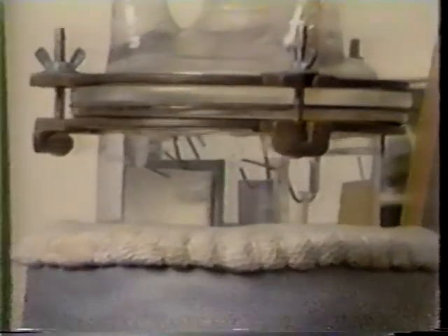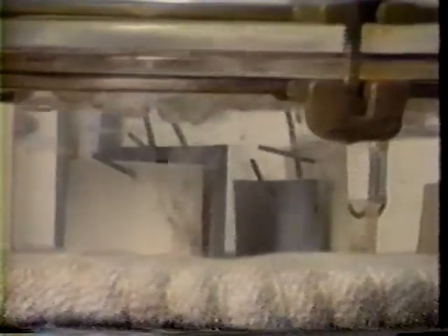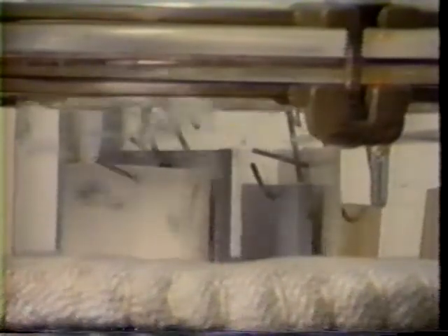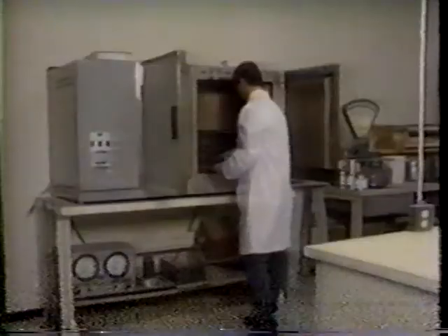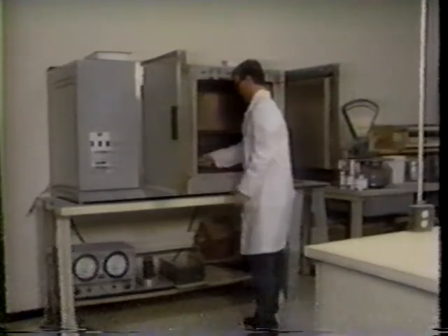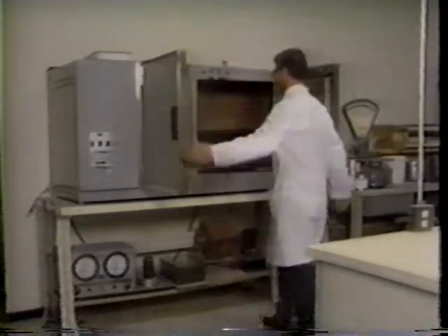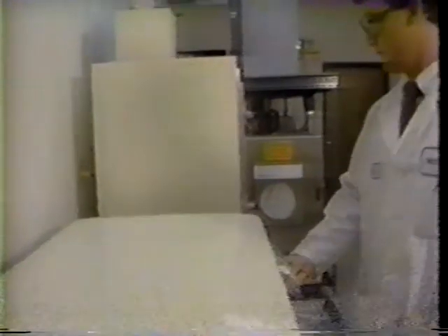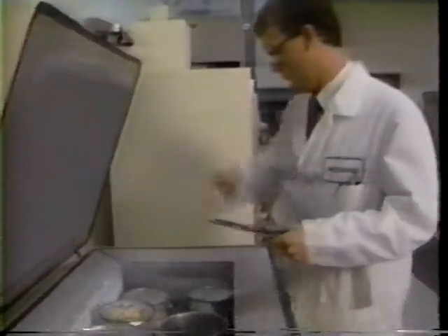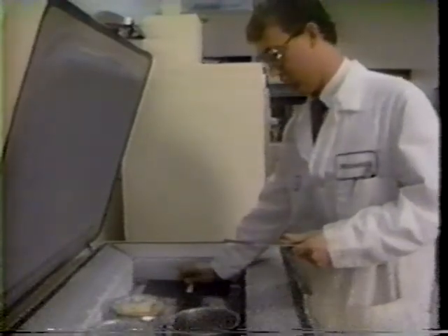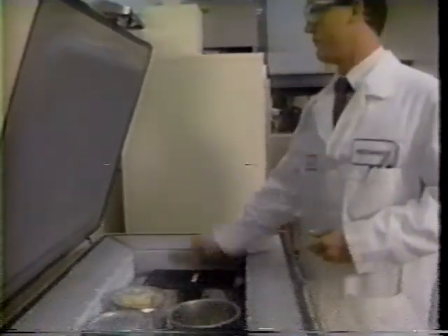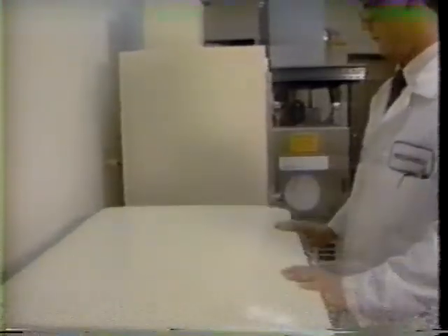The resin's properties, evaluated before and after exposure to these severe conditions, were significantly higher than the results of competitive conventional and high-performance resins. Gel-coated laminates were exposed to temperatures as high as 200 degrees and as low as 20 degrees below 0 Fahrenheit, and evaluated for strength and resistance to cracking. Hydrex resin showed excellent stability under this rigorous testing program.